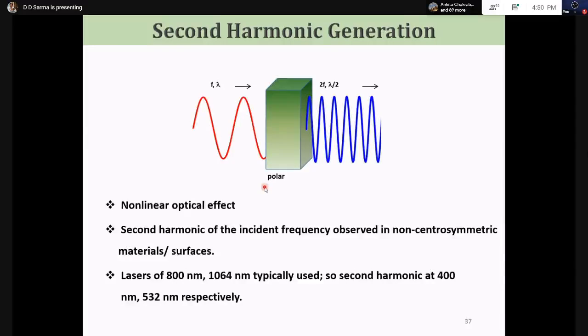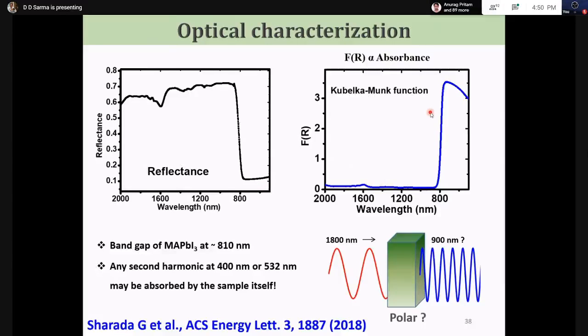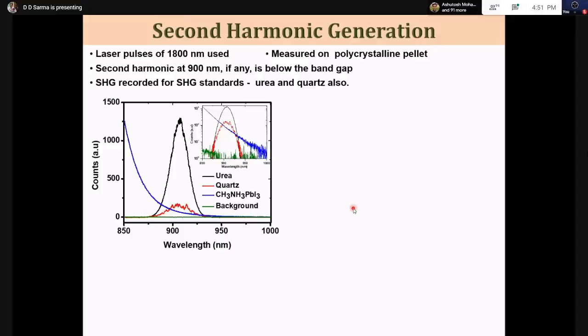So we did this experiment, and there are some technical aspects which have been dealt with in detail in this particular paper, because many people did the experiment wrongly. You have to choose your incoming wavelength to be very long. We used 1800 nanometers, such that the second harmonic, half the wavelength, 900, is still below the absorption edge. This is the absorption edge. So we did this experiment, and what we find is shown over here.